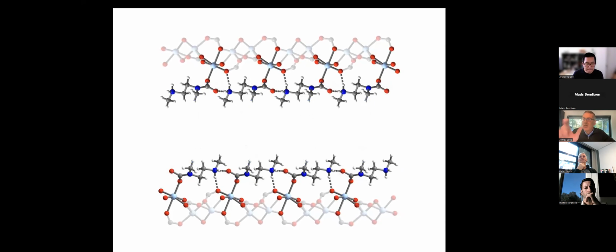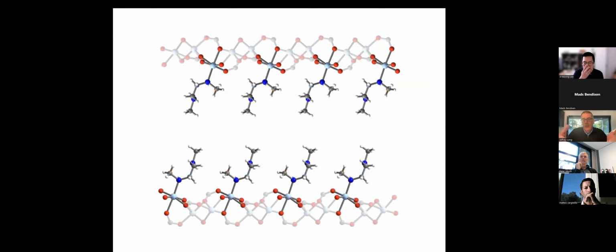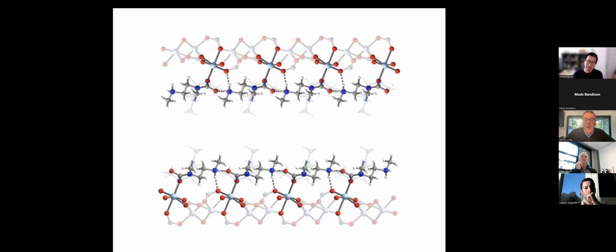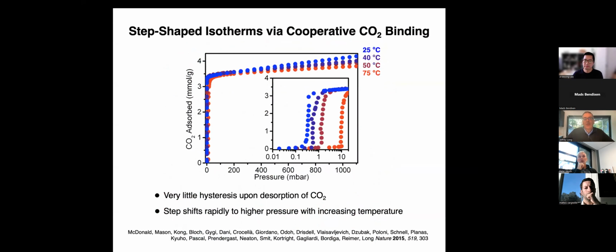And so here we got very lucky. The ethylene diamine is just the right length to bridge CO2 adsorption sites and create a cooperative polymerization adsorption process. And so this material indeed shows very nice step-shaped adsorption isotherms. And this is the first observation of such steps and cooperative adsorption for CO2 under such conditions that might be relevant, say, to capture from a flue gas or even from air directly.